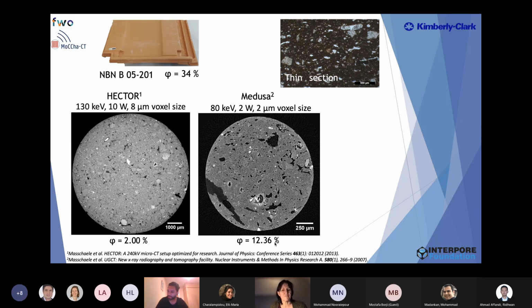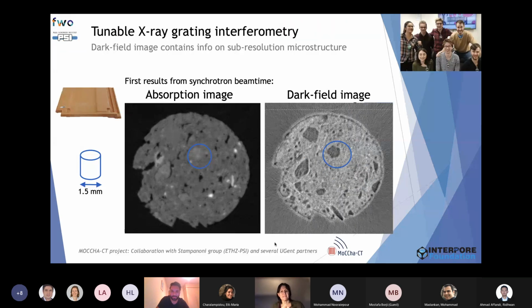So we went to the synchrotron to test the idea of grating interferometry, and this is the result. On the left, you see we took a sample of 1.5 millimeters and scanned it with absorption, and scanned it in the dark field using the gratings.